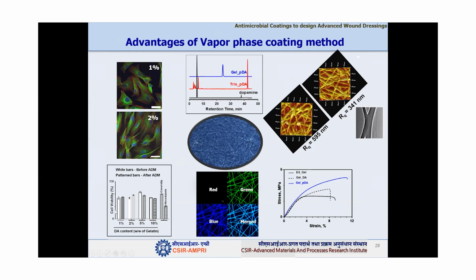The viability studies show that there is no reduction in the cell number when we are using these coatings. That means these coatings are very safe. And very interestingly, when we coat the gelatin nanofibers with these coatings, they show fluorescence properties also. This is actually unexpected. We never expected it. When we were looking at the cells, we saw the fibers are also colored. That is how we got to know that the nanofibers have fluorescence properties also.